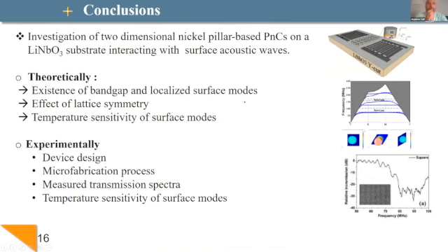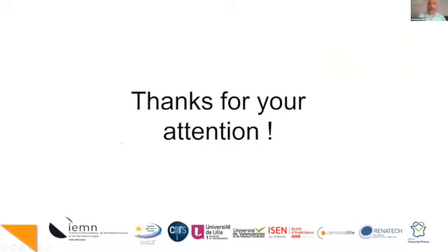In conclusion, we show in this presentation the investigation of a surface phononic crystal deposited on lithium niobate, and we bring out the existence of a band gap and the existence of a surface mode. We also demonstrate that the temperature sensitivity of the surface mode can depend on the design of the phononic crystal, in this case on the lattice symmetry, and we demonstrate all these theoretical results experimentally, both the transmission, the measurement of the surface mode, but also the analysis of the temperature sensitivity of the surface mode. Thank you for your attention.